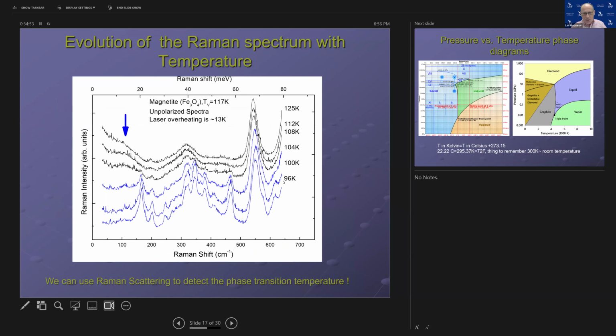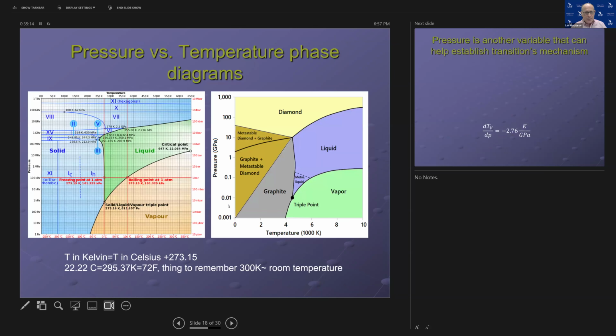You can change temperature with small increments, and you see that the transition is quite abrupt. Those additional modes are clearly seen. So that allows you to immediately find the transition using Raman scattering. The next thing I'm going to talk about is the phase diagram, which is related to this phase transition.